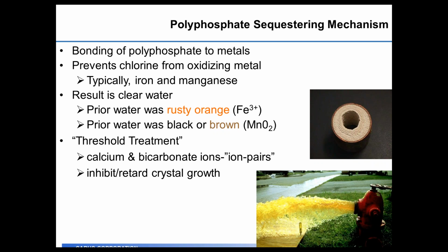The other thing that polyphosphates do is called threshold treatment. They prevent the calcium and bicarbonate ions from pairing together and forming calcium carbonate scale. What happens is you'll retard that crystal growth, and you won't form the scale that you see in the pipe on the right-hand side of the picture. Why do we want to prevent that? Obviously, that pipe is severely restricted with that much calcium carbonate scale. For corrosion control, you would love a thin scale of calcium carbonate, but you don't want it to keep building on itself to the point where it actually restricts the pipe.